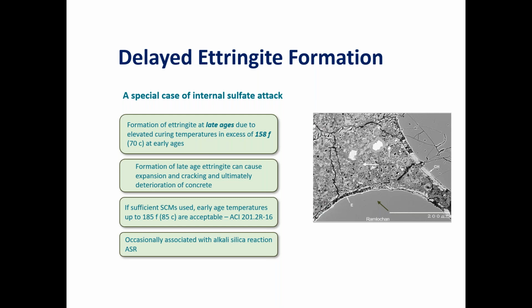And this ettringite formation, as you can see from this picture, it looks like my arrows kind of went a little off, but that green arrow is pointing towards a little dark band that is sort of at the edge of the aggregate. What happens is that after the concrete is hardened, this ettringite forms and it starts pushing between an aggregate particle and paste particle, and you can see the white lines are generally pointing towards these cracks that have evolved. And so this is the ettringite here. If you look above that, you see this crack pattern. Well, this is stress that's built up because you have this ettringite forming in between your hardened paste and your aggregate particle. And if you look back over to the right, center right, you can see the white bands that are labeled CH. That's calcium hydroxide. So that's the stuff that you want.